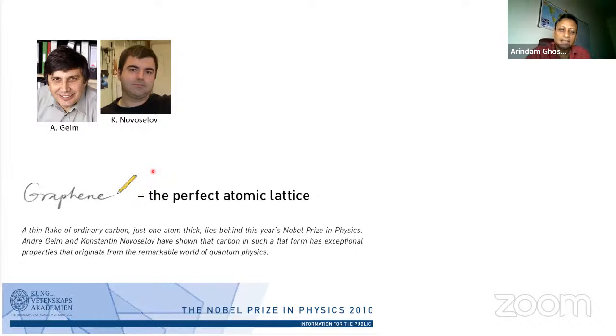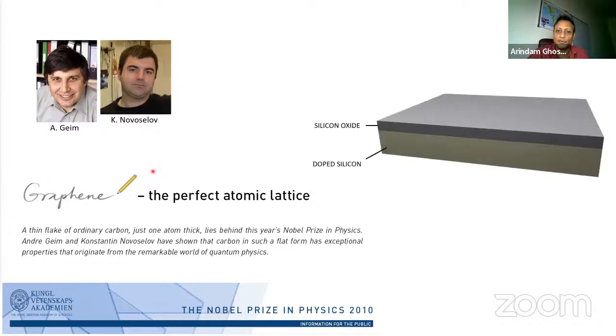The interesting part is the way they did it, simply because this was extremely easy and something that can be tried even in schools and colleges of separating graphene out of graphite. It's very simple. What they did, they took a substrate, which is of silicon, and then oxidized the top surface, making it silicon oxide. And then they used a simple tape. You have the sellotapes at home, and put graphite on that, and then you press it on the silicon oxide surface, and then discard the tape.